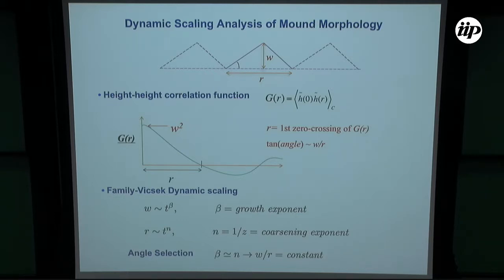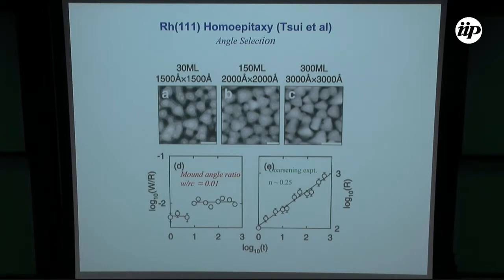In the experiments, I will show you the experimental data, but you can see from the pictures that what you are seeing during mound formation is not that you have mountains that are getting steeper and steeper. What you're finding is that these mounds run into one another and they coarsen with time. Their sizes get larger, but the angle is fixed. So this angle, whose tangent is just W over R roughly, is constant. What it implies already, if you assume that this angle is fixed, like a particular surface, the plane is selected, is that these exponents must be similar. Beta must be equal to n in order for W over R to be constant with time. And so I'll show you the experimental results. There are a variety of experimental results, and this one is particularly from Tsui's experiment on rhodium.